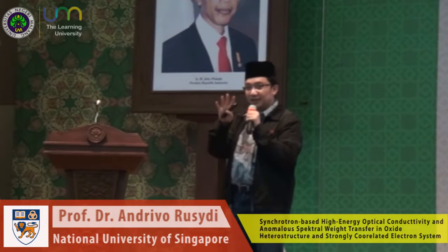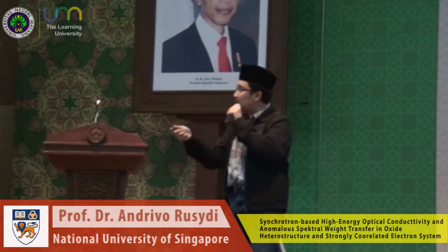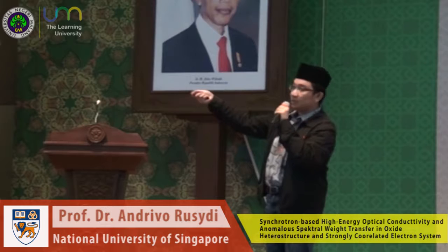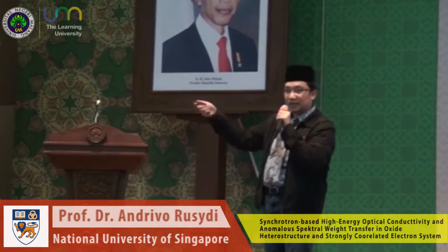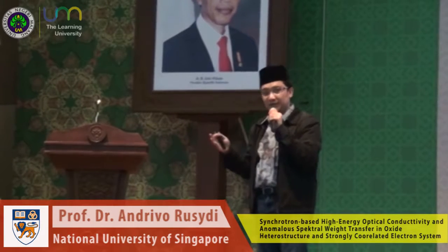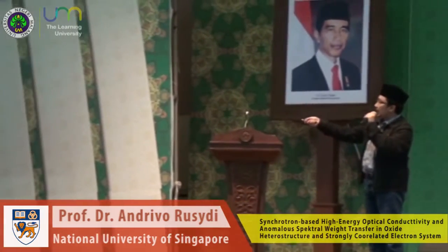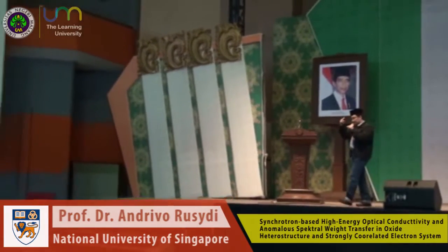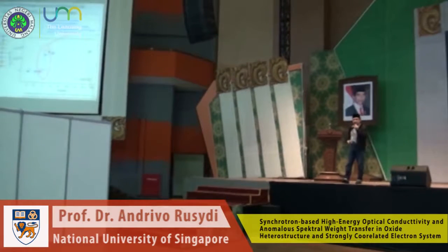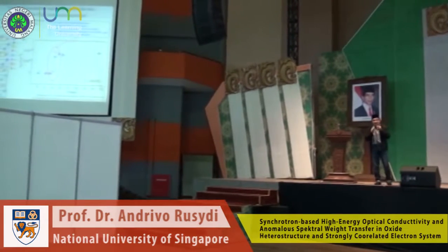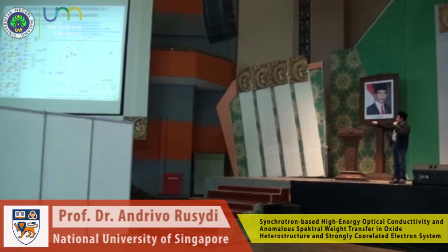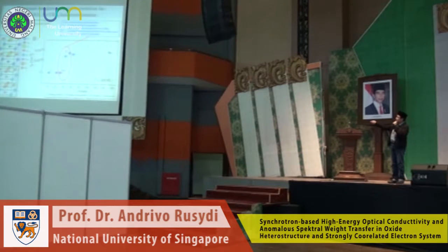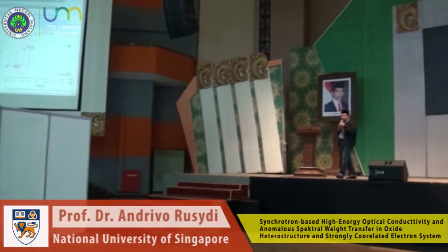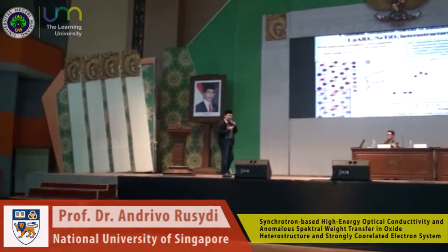The questions that the field would like to understand are four important observations. First, there is the so-called insulator-metal transition. Look at this, insulator to metal as a function of thickness. Then a sharp transition: only adding 1 unit cell. You add another lanthanum, another aluminum, and 3 oxygen, and it becomes a metal. That does not happen in nature. And even though you add more layers, it remains constant. The sheet conductivity here is proportional to about 0.05 electrons involved in the transport measurement. That's what we want to understand. Can we understand such a phenomenon?